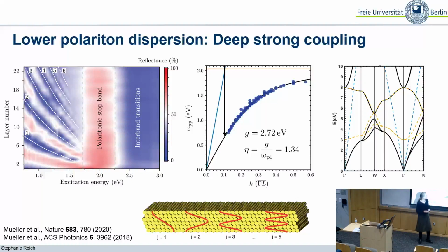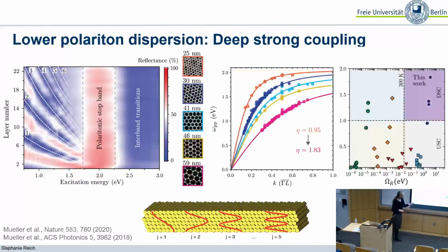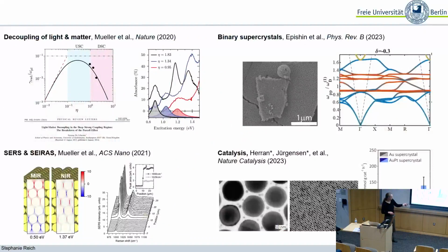Where we saw a difference was this one here. So the cesium chloride structure, we can clearly see that we also get these peaks due to the plasmon polaritons, but they are at different frequencies. And we could then trace that back to the change in the dispersion of the plasmon polariton because we have a different crystal structure.